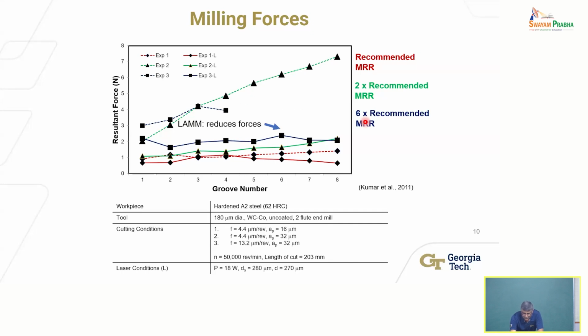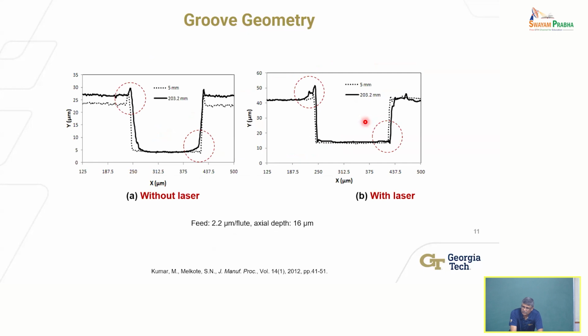All right, so the tool breaks. What happens to the shape of the geometry that you're producing, in this case a simple groove? Well, this is without the laser. And what you see here is the groove after cutting 5 millimeters only in terms of length of cut, and after 203 millimeters. After cutting 5 millimeters, this is the dashed line, looking at the cross section of the groove, you can see there are what you can call burrs on either side, essentially material being displaced, right?